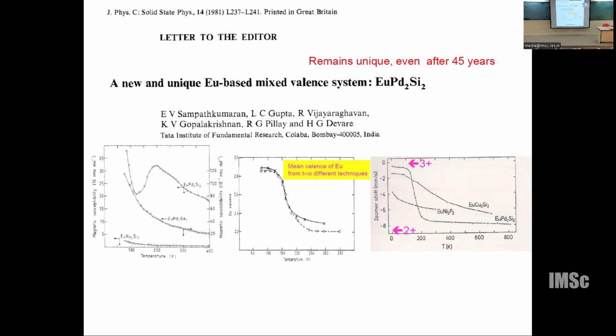You could find the isomer shift. If it is trivalent, it should be close to 0 with reference to europium trifluoride. If it is divalent, it will be somewhere here. For a stable valent compound, it will be practically temperature independent. That is established. But in this compound, you can see almost a 3+ state to almost a 2+ state, a very huge valence change over this range. So you can determine the valency from this isomer shift, taking the 3+ reference and the 2+ reference, and plotting it against what you determined from susceptibility. There is a fairly good trend.